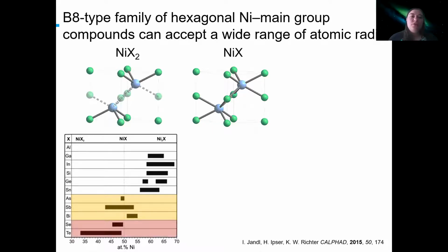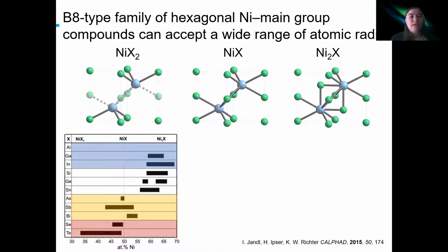And then if you start removing some of the nickel atoms in the central every other layer, you get to the structure that's adopted by selenium and tellurium. And if you go all the way to the other side and start adding in an additional nickel site into the structure here, then it's adopted by the aluminum, gallium, and indium.